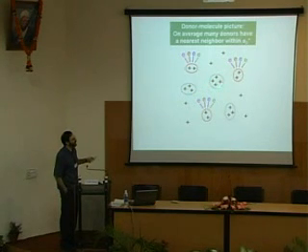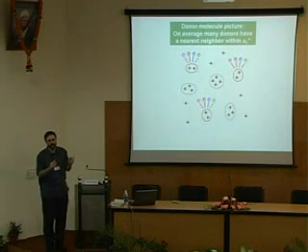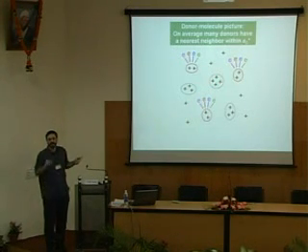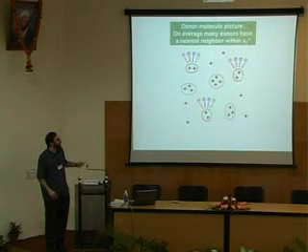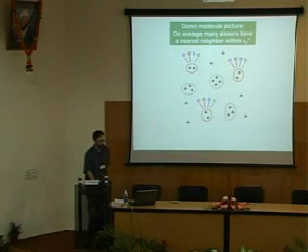If we have 4 dopants that are close together, that's going to be a very low energy where the first electron wants to go. If I was an electron sitting here, I'd say that's the first place I want to go. It's the most positive charge. That's the kind of cluster that would explain these very first peaks that we see in the data. These would be later on at a higher voltage, where things are giving rise to the effects of peaks A, B, and C.